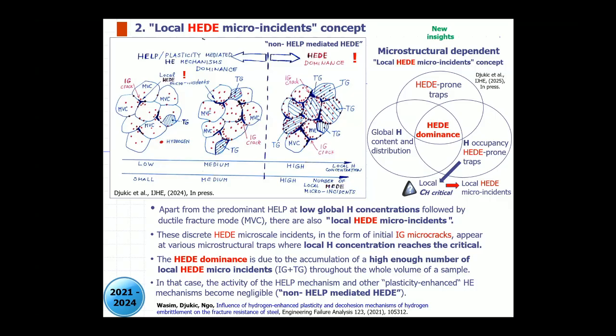So that's the concept. Hydrogen occupancy is also very important. And we try to show here that at small concentration, we have a local HEDE micro-incidents. As you can see, we have HELP, ductile predominance, which means that the material still behaves in a ductile manner. But when the material is ductile, it doesn't mean that we don't have local spots of brittle failure in the material. But for example, in the brown area, we have a localized HEDE activity, but generally speaking, the material still has good HELP activity and predominance of HELP or some other mechanism.